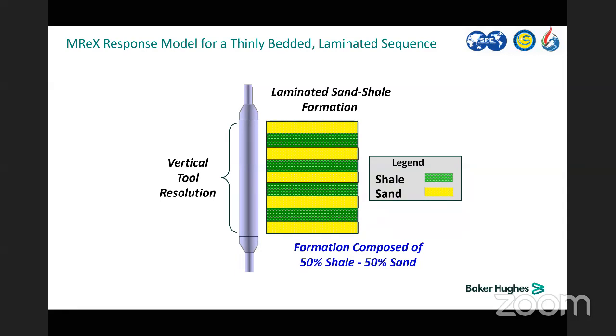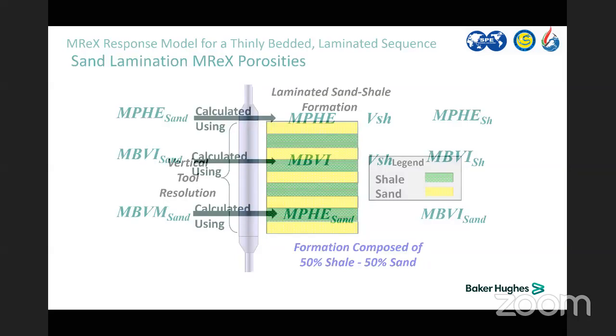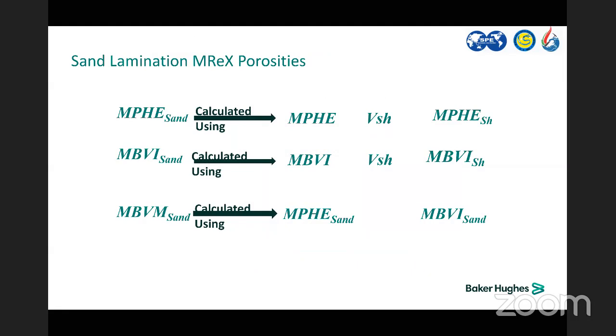This is the normal sequence of shale sand lamination and the tool vertical resolution. All we did, as I mentioned, was quantify the shale volume and effective porosity, which is the lithology independent porosity, and the effective porosity in shale. We are able to identify the MBVI for sand, and from the MBVI of sand, we are able to identify the MBVM, which is the free fluids inside the sand.